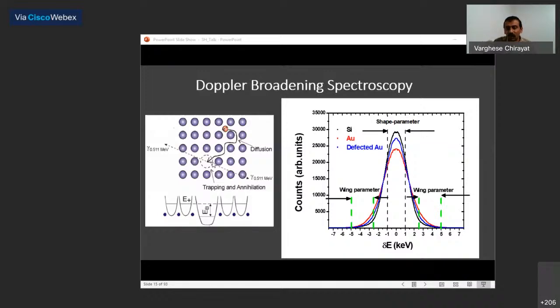What you get is coupled information. You will see a variation in line shape, whether due to an increase in defect density, which means you are increasing the number of defects, or you will get a change in line shape when you change the defect type. Say, for example, you are going from mono vacancy to di vacancy, or di vacancy to a 4 vacancy cluster, and so on. So both of these will give you a change in line shape, and it is difficult to decouple these two changes. But the overall thing is that you will see a change in your line shape, which is a combination of either the defect density changing or the defect type changing, or both of them changing. And you will get the information about the chemical architecture at the site of positron annihilation. So I hope it is clear till these two points.